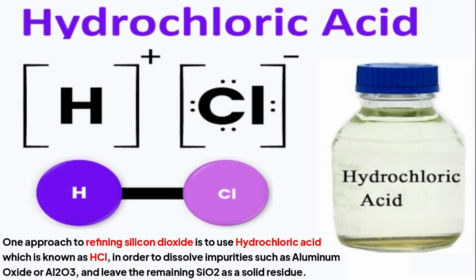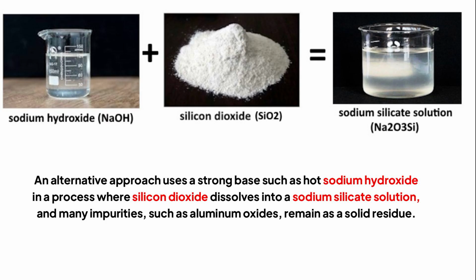One approach to refining silicon dioxide is to use hydrochloric acid, which is known as HCl, in order to dissolve impurities such as aluminum oxide or Al2O3, and leave the remaining SiO2 as a solid residue. An alternative approach uses a strong base such as hot sodium hydroxide in a process where silicon dioxide dissolves into a sodium silicate solution, and many impurities, such as aluminum oxides, remain as a solid residue.